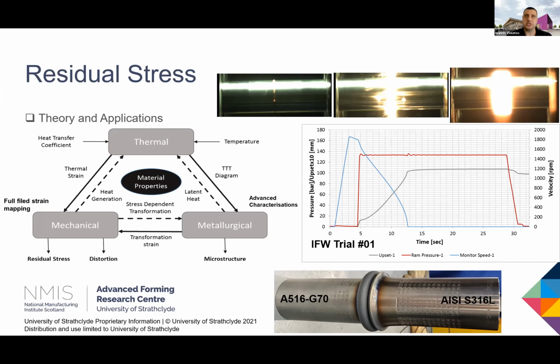Obviously, all of these are well known and can be accommodated. Specific information regarding each mechanism, we are probably lacking. We need to do a bit more testing, but we also have quite a number of options with other software like JMatPro or some first principles calculation. What I would like to point out is that throughout the welding schedule, we will have that increase in temperature, we will have the applied force, we will deform the material quite significantly, and then the material will cool down. So obviously we are measuring stresses at the very end of the process at an equilibrium condition, room temperature. We are not measuring those applied stresses.